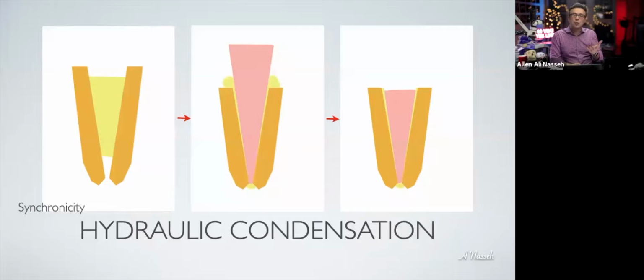The reason this technique works so well is that it uses the sealing ability of the bioceramics, but instead of using the full bioceramic to seal the canal, which would make it very difficult to retreat, we wanted to develop a responsible technique that could be retreatable. So the idea of having a main cone that fit and filled the main part of the canal allowed not only control of the sealer all the way to the apex, and a little bit of hydraulic pressure sideways so we can push the sealer into the nooks and crannies of the canal, but more importantly, also provided a path for revision. If a case is still not cleaned and shaped adequately, or if we need to go back down the line and revise this tooth, we can easily do the revision by melting the gutta percha in the center and then removing a layer or two of the dentin on the side and getting good cleaning.